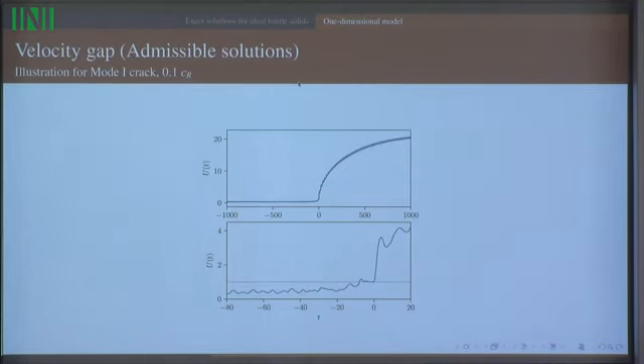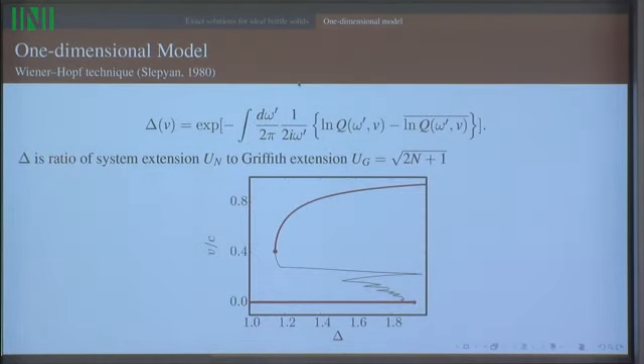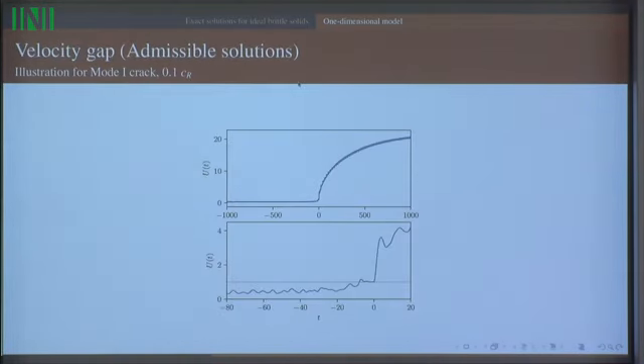So let me come back now to the point of admissible solutions. These solutions down here, all this jagged stuff which looks so interesting, these are not physical once you impose the condition that t equals 0 is the first time at which the bond will break near the crack tip. And I have illustrated this with solutions from a very elaborate model. So this is one with infinite numbers of degrees of freedom, with cracks moving in plane.